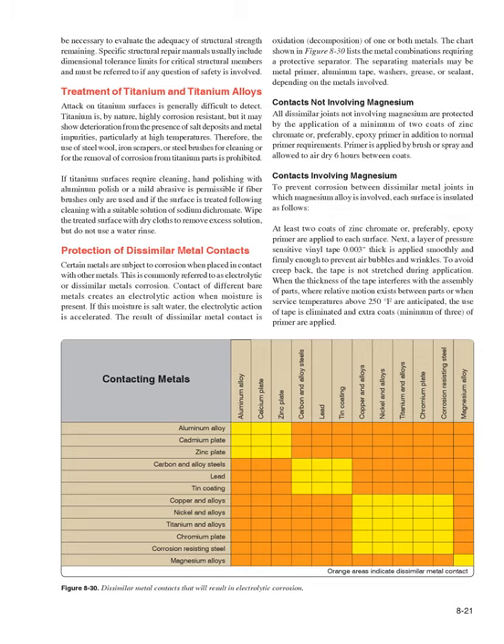Therefore, the use of steel wool, iron scrapers, or steel brushes for cleaning or for the removal of corrosion from titanium parts is prohibited. If titanium surfaces require cleaning, hand polishing with aluminum polish or a mild abrasive is permissible if fiber brushes only are used and if the surface is treated following cleaning with a suitable solution of sodium dichromate. Wipe the treated surface with dry cloths to remove excess solution, but do not use a water rinse.